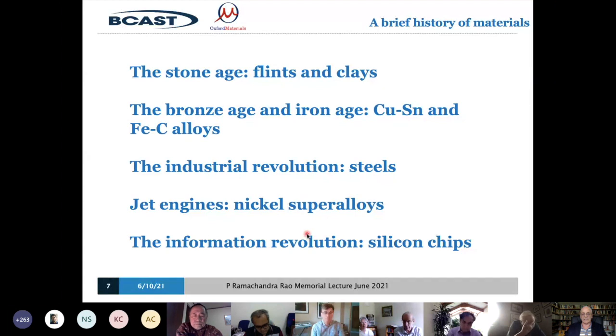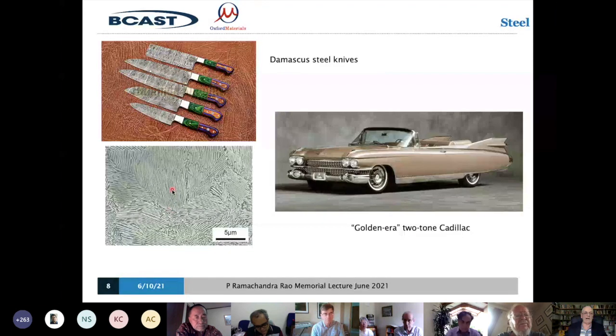So just some quick pictures of these things. Here's Damascus steel knives, very beautifully made with these beautiful patterns. The patterns arise from the alternating layers. This is at the relatively high level of about 0.8% carbon. And these are alternating layers of pure iron, which gives the softness and the formability into these shapes, and the iron carbide cementite, which are the other colored layers, which then when made into the object, give these beautiful pictures.